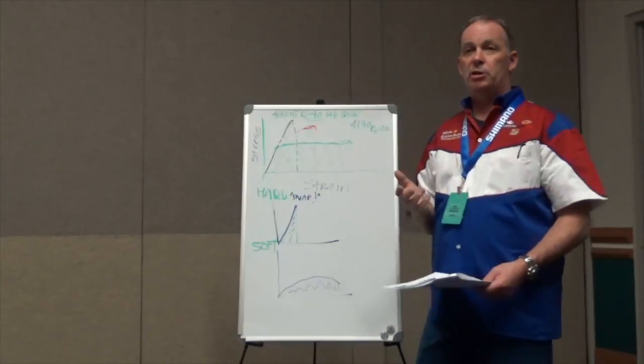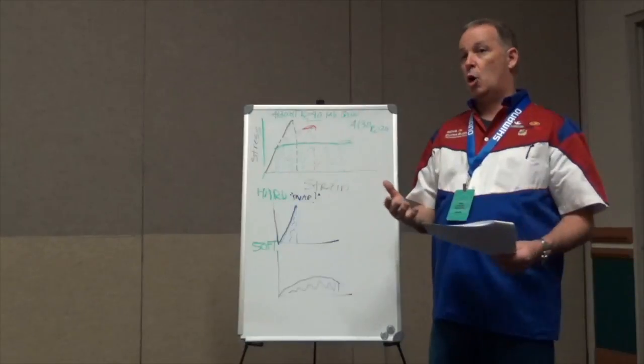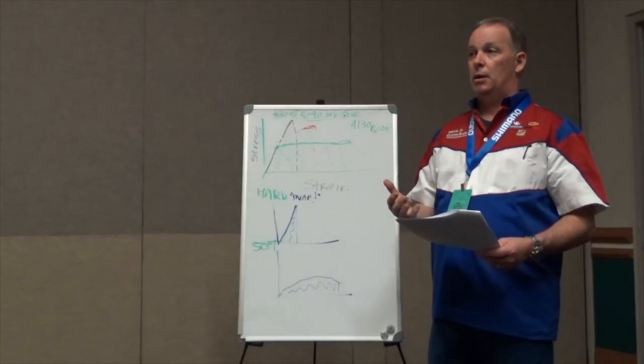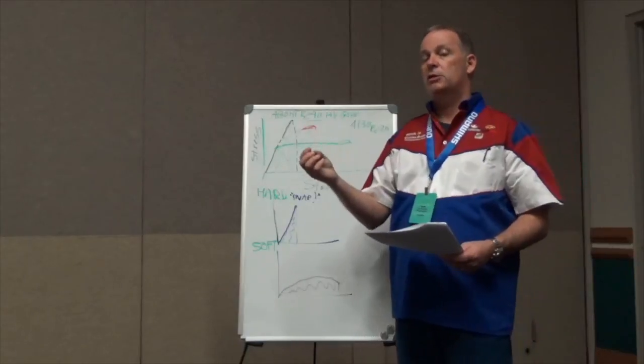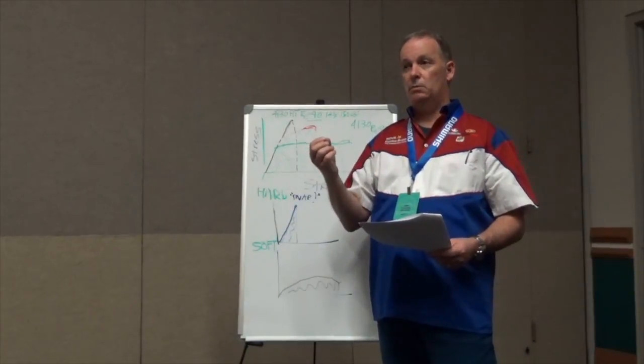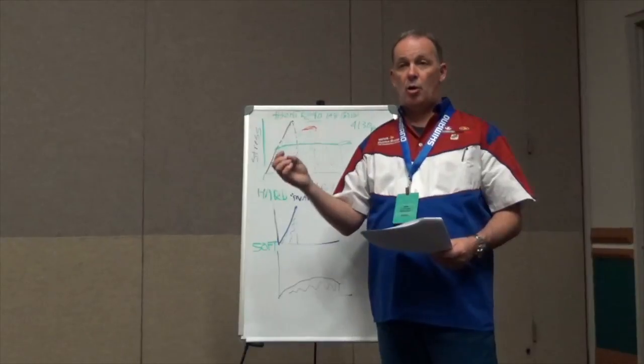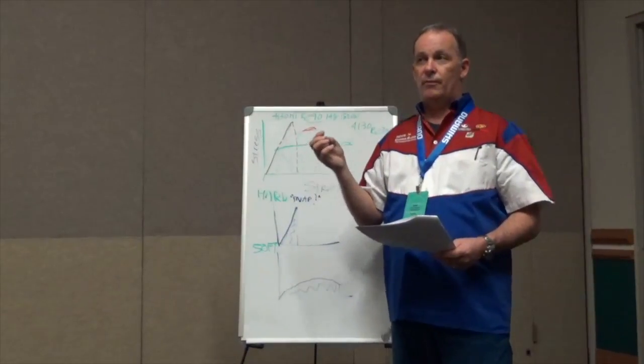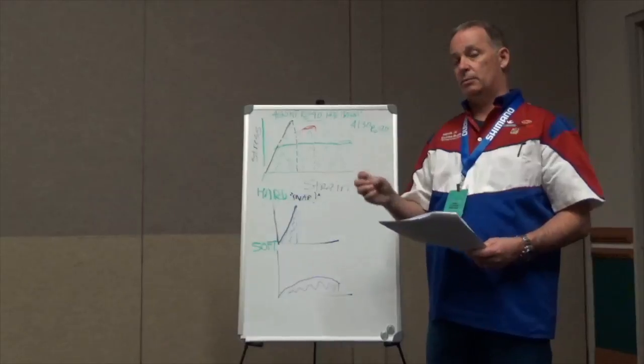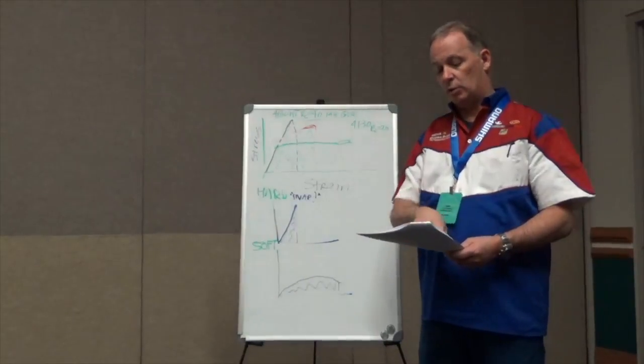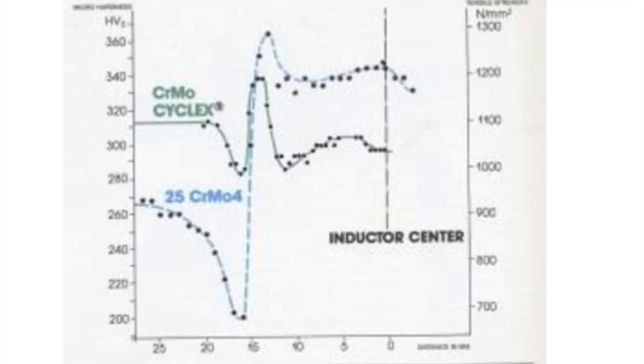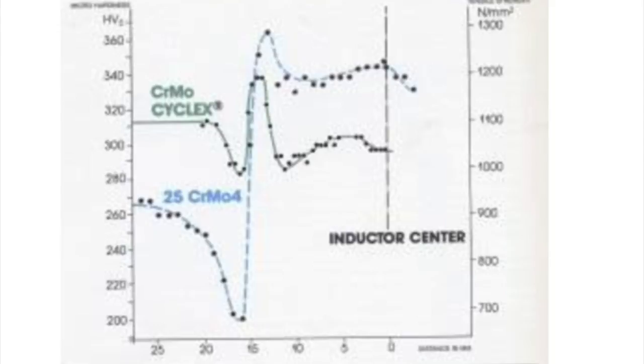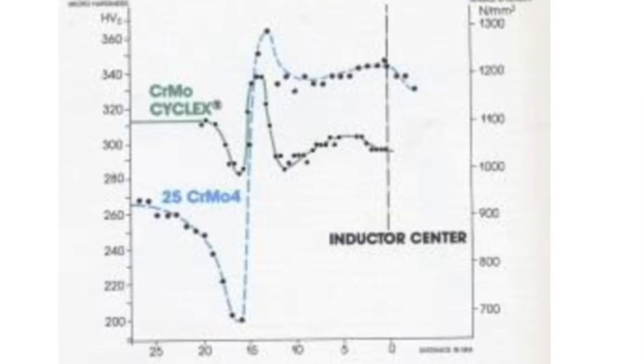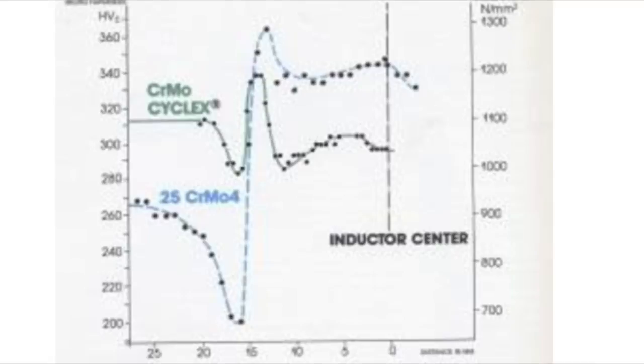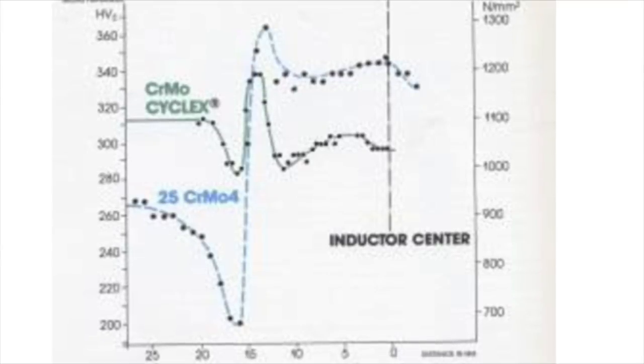This is what happens when you weld a tube. And we hear a lot about air hardening, and the companies that talk about an air hardening steel that they use in their tubing, they are indeed air hardening materials, but the phrase without context is a little bit misleading, and I'll show you why when you look at this graph. Virtually all materials in bicycle frames, because the wall thicknesses are thin relative to the geometry of the tubes, all of those materials are air hardened. It's because they cool rapidly.